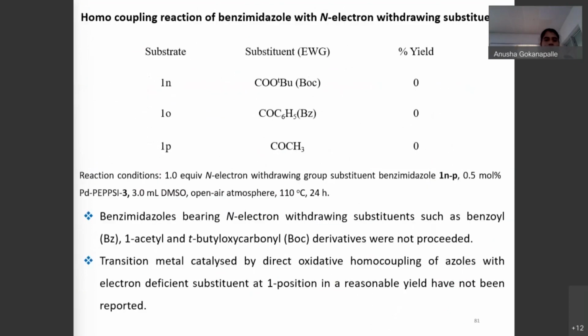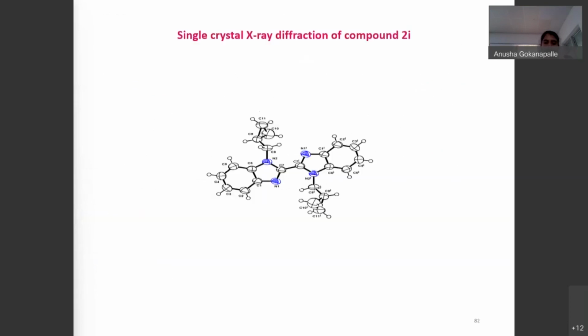Homo coupling reactions of benzimidazole with N-electron withdrawing substituents. Benzimidazoles bearing N-electron withdrawing substituents such as benzoyl and N-acetyl tertiary butyl oxycarbonyl derivatives did not proceed. Transition metal catalyzed direct oxidative homo coupling of azoles with electron deficient substituents at one position in reasonable yield has not been observed. This is the single crystal XRD of 2I compound. This is the evidence for the formation of bisazoles.